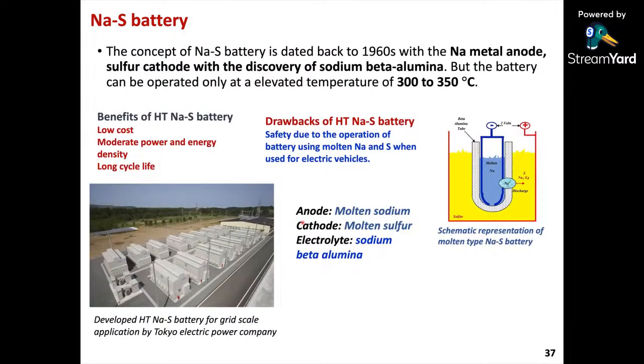Okay. Finally, move on to sodium-sulfur battery, and we know that high temperature sodium-sulfur battery is in use with molten sodium and sulfur. And the electrolyte is the sodium beta alumina. But there are lots of drawbacks with reference to this, mainly because you have to operate it at a very high temperature, 300 to 350 degrees centigrade. So the question is, is it possible that we can get room temperature operation of your sodium sulfur battery?